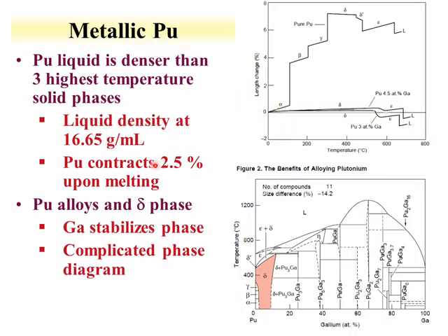And here's an example figure showing the phases as a function of temperature for plutonium metal and plutonium alloyed with gallium. We see that the gallium phase, the delta phase, is stabilized over a very large regime. Lattice change or length change is minimized until the temperature is reached where the epsilon is formed, and then liquids are also formed. And we see that there's consistent behavior with these alloys.